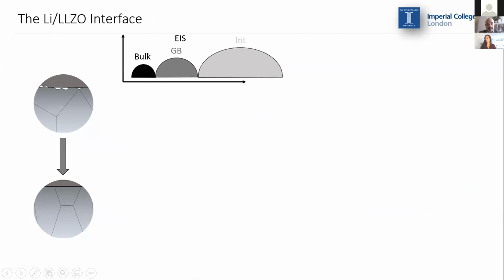By recording electrochemical impedance spectra, we generally end up with three semicircles, like I'm picturing here. One will describe the bulk, one the grain boundaries in between LLZO grains, and one will define the interface. So we want to have the semicircle defining the interface as small as possible, and that will indicate a good contact between metallic lithium and the solid electrolyte.